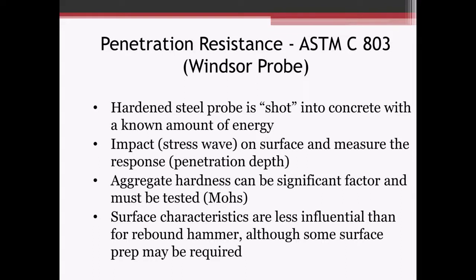So next we'll talk about penetration resistance, ASTM C803, more commonly known as a Windsor Probe. You've got a hardened steel probe that's basically shot into the concrete with a known amount of energy. On impact with the surface, we're measuring the penetration. It's obviously putting some stress in the concrete. We're measuring the penetration depth. The deeper it penetrates into the concrete, the weaker the concrete is. It is based, to a certain extent,